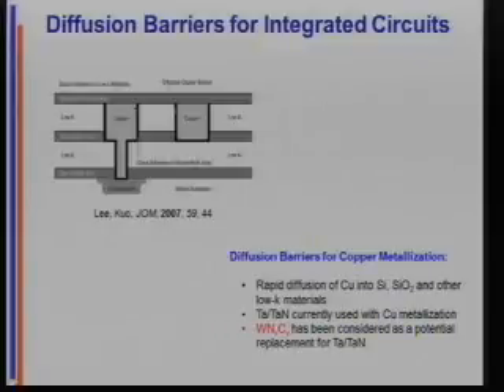And that was causing a giant kerfluffle because copper migrates through the old titanium nitride barriers that were used with aluminum-based chips. And so along with that was the problem of feature sizes on the chip getting smaller and smaller and smaller. So the layers are getting thinner, the demands of aspect ratios are getting more stringent. And so they needed to figure out not only a way to put something in here and not block up the whole feature, but also figure out what material would block copper diffusion.